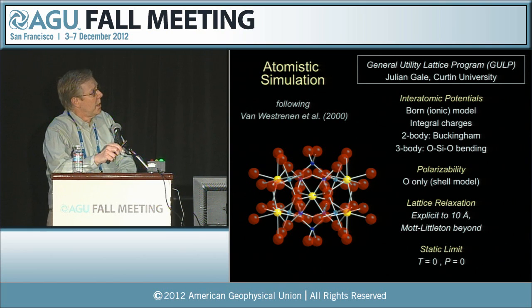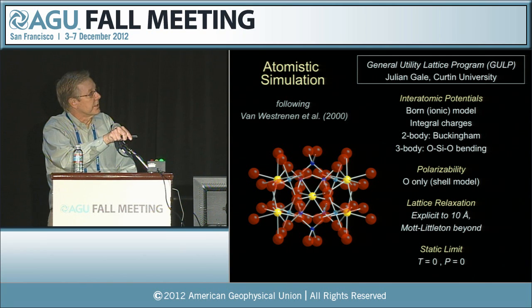We follow the protocols of Van Westrenen et al. That means the interatomic potentials are Born ionic models with integral charges, two-body Buckingham potentials, plus a three-body term for oxygen-silicon-oxygen bending. Polarizability is treated with a shell model, but only for oxygen. Lattice relaxation is explicit out to 10 angstroms and with a Mott-Littleton approximation beyond that, and all of these are in the static limit. So we have to focus on the structure of garnet.